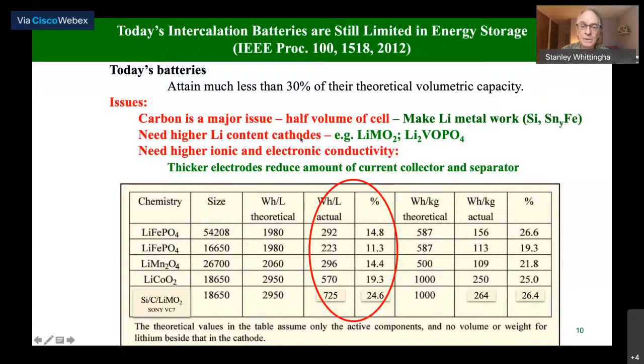We've also got to get a higher lithium content in the cathode. So this is a layered oxide. In fact, we only use about 60% of the lithium. I'll get into that a little bit later. But from a solid state chemistry point of view, what we need are higher ionic and electronic conductivities. We can then use thicker electrodes. If we can use thicker electrodes, we can get rid of half the current collectors and half the separators. So that's really where most of the research is going.